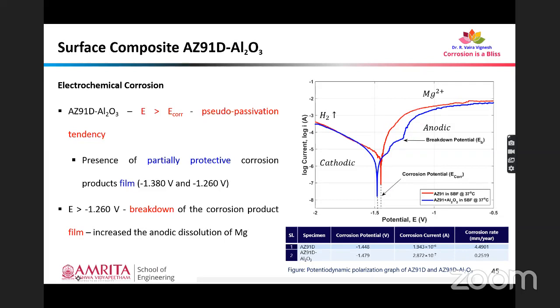Why? Because there is limited current after corrosion potential. So we can confirm that there are partially protective corrosion product films forming right from minus 1.38 volt to minus 1.260 volt. So that resulted in enhanced corrosion resistance of the surface composite. Added to that, if the potential is increased beyond this minus 1.260 volt, that is the breakdown potential, beyond which the surface composite is also subjected to high corrosion rate. But within this region of interest, we have very low corrosion rate.